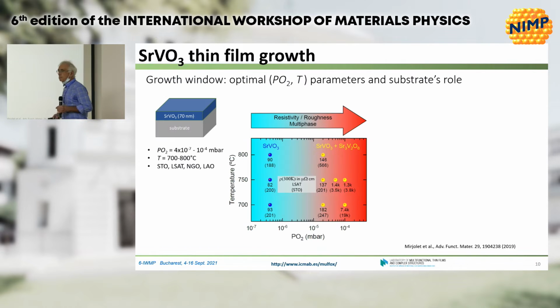So the strontium vanadate films, and this is also true for strontium niobate, require very harsh conditions, or extremely reducing conditions, and it is very challenging to get films of high conductivity. Films in Barcelona were grown by PLD, and this plot indicates that you need high temperature and very low pressure to get the optimal materials, otherwise you get a mixture of phases.